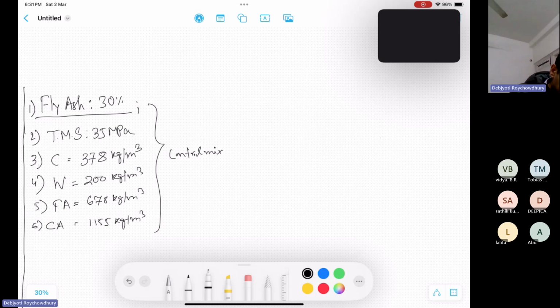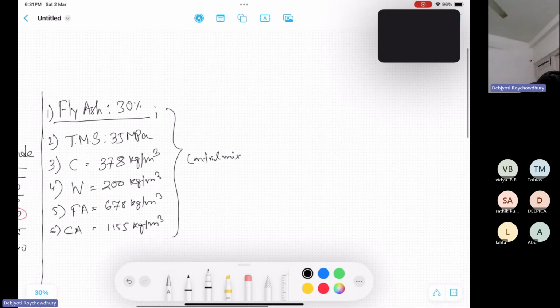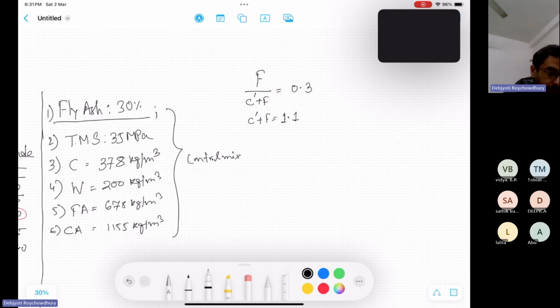Two formulas are available. One is C dash plus fly ash content, where C dash means the new cement content. The fly ash proportion is 30%, so 0.3. Whenever we add fly ash in the concrete system, it promotes larger volume, so larger mass. So it is 10% increased, so it is 1.1 C. What is C? 378. So 378 into 1.1 is 415.8 kg per meter cube.